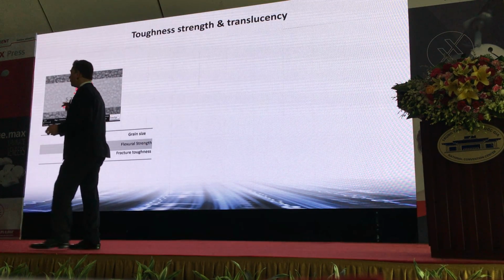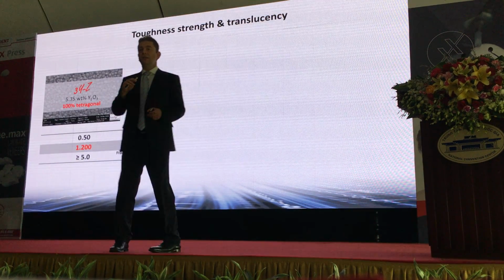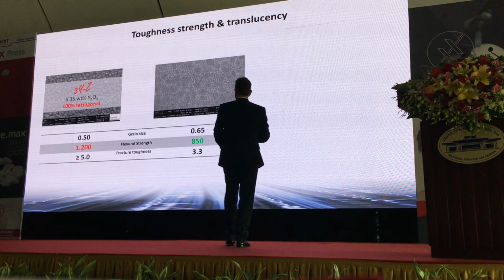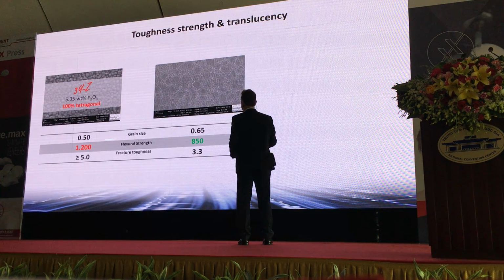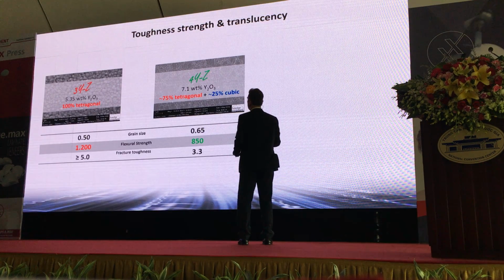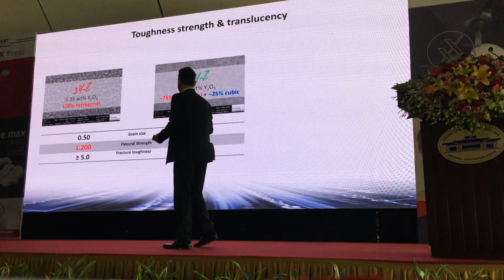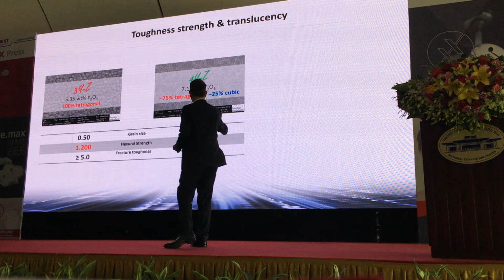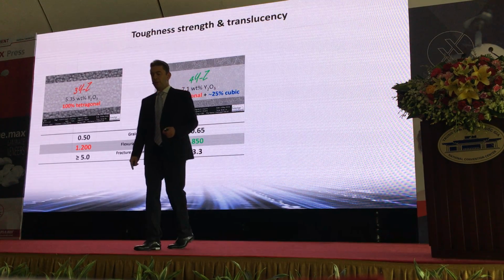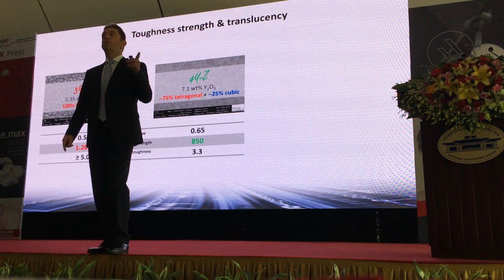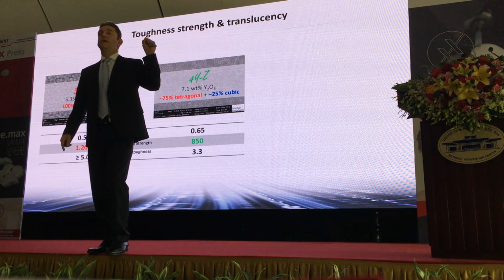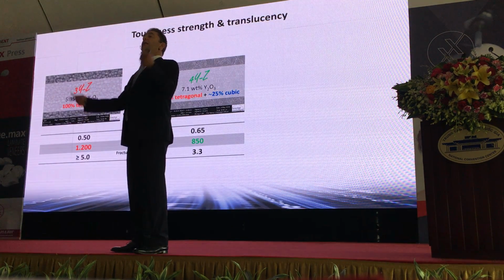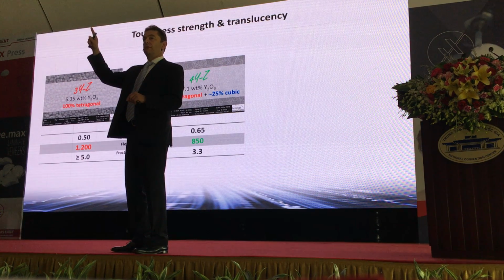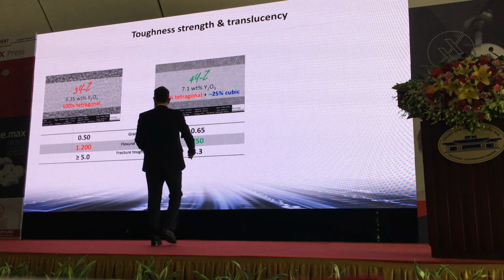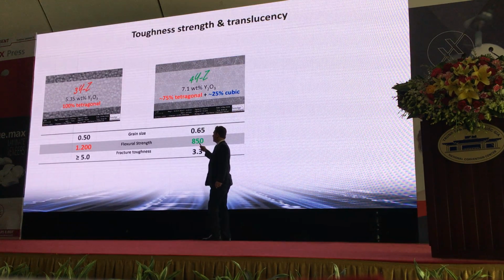Now if we increase yttrium oxide in this zirconia, you can see the crystals are changing. Crystals becoming more large. So now we have 4 mole percent, so more yttrium oxide in the material. And now we have a share of 25% of cubic polycrystals. Remember Swarovski? Swarovski is only cubic, more translucent. So now we have 25% of cubic, and the material becomes more translucent. However, it becomes also weaker, because from the 1200 we have now only 850.